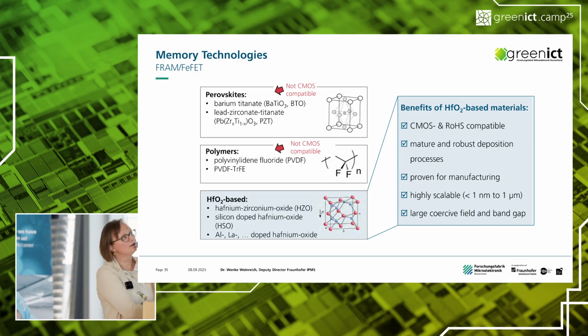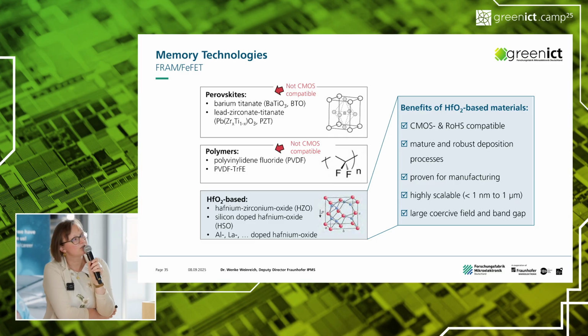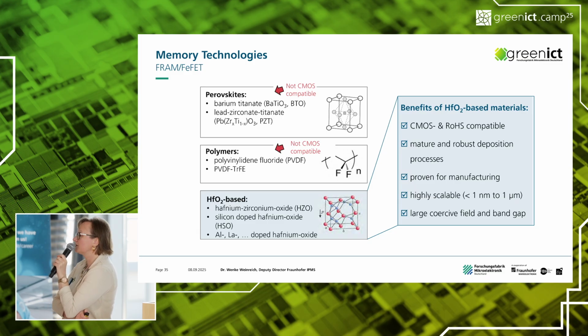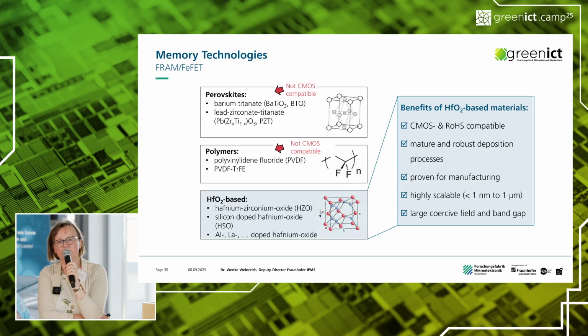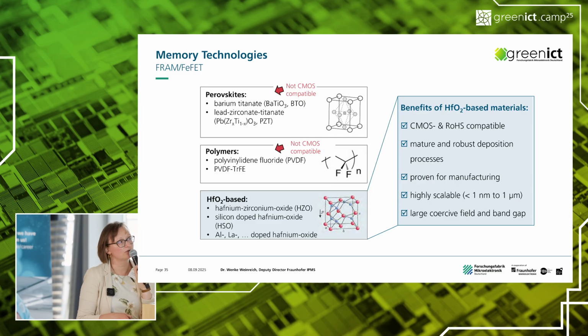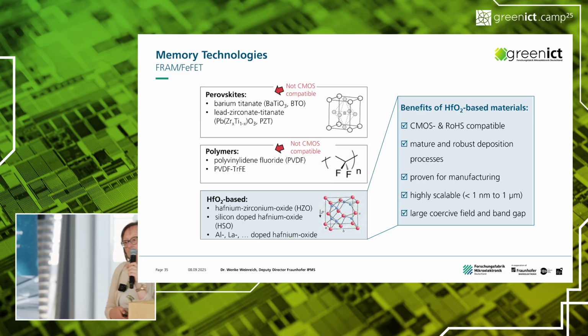So luckily, between 2006 and 2009, a PhD student at a memory company here in Dresden found out that our high-k metal gate material hafnium dioxide that you have in a CMOS is also ferroelectric. So this was a real big invention one of the PhD students made here in Dresden, because he found out if you dope hafnium oxide a little bit with zirconium or with silicon or something else, you can make it ferroelectric. And that was really a good thing.